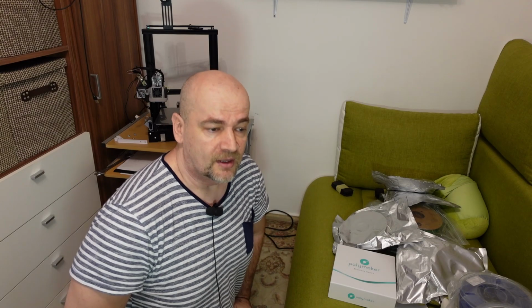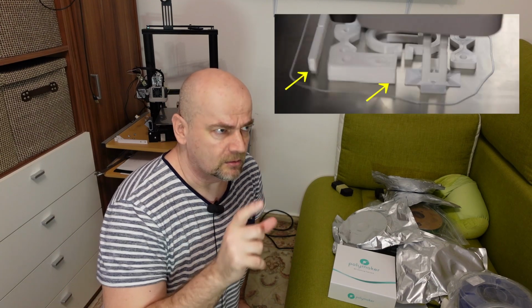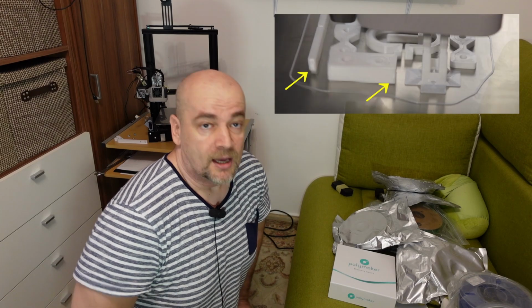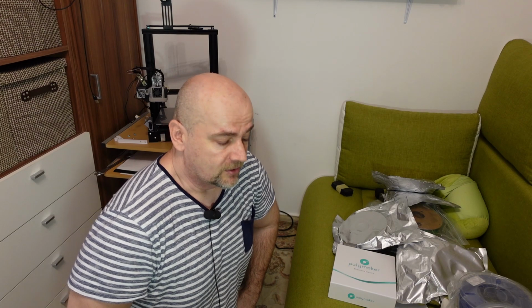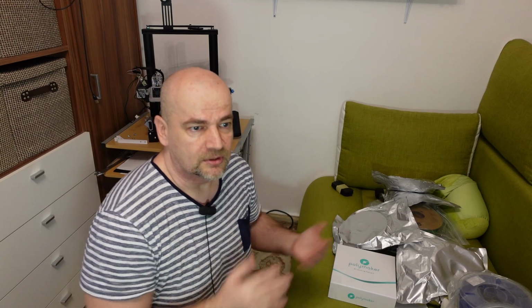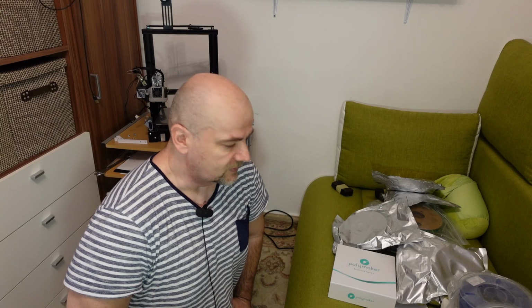About these same materials: yes, the PolyMax polycarbonate was the strongest, but it is the hardest to print, so it requires higher temperatures, and it's better to print inside an enclosure. And don't forget to use the brim. I didn't use it, so I got warping on 2 elements. Of course, the easiest to print is the PLA. But don't forget, the PLA unfortunately will deform a little bit above 50 degrees Celsius. So if you forget your part inside the car on a hot summer day, it will deform. So PETG is a little bit better solution if you need a little higher temperature resistance.